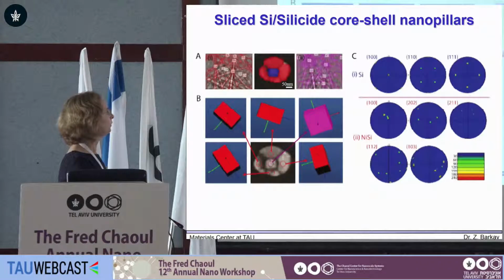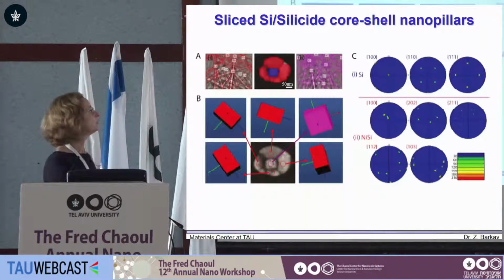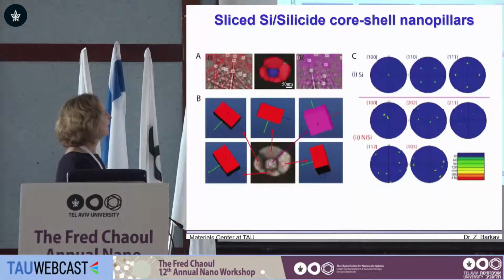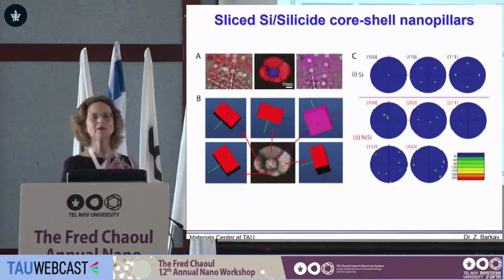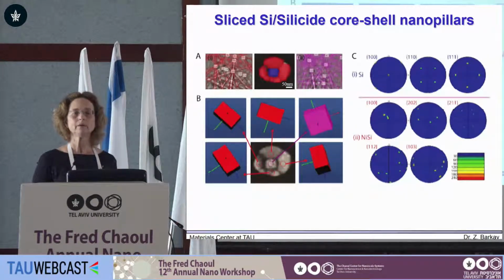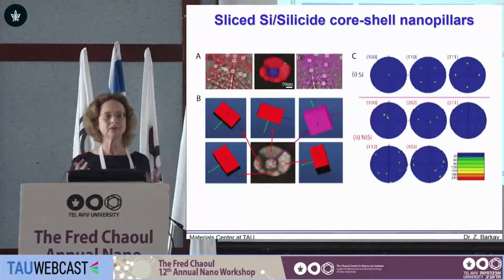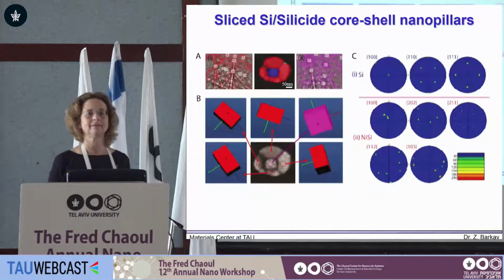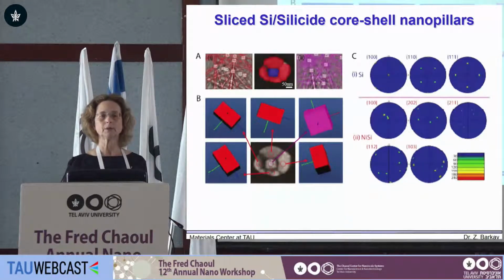If we look at this pole figure configuration and look for the 100 direction, you see that if it is in the silicon perpendicular to the sample, the 100 for the nickel silicide is a bit deviating. So it's a very easy way to get orientation information, not as easy with other types of methods. And very good resolution - not atomic resolution, but nanometer resolution, which is very sufficient for many, many applications.